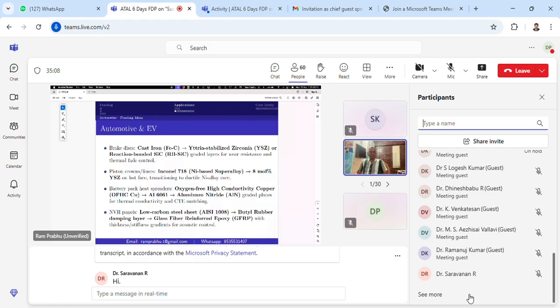So currently cast iron is used because you have a graphite lubricant inside and it has very good tribological properties. But when I expose this cast iron to the high energy braking conditions, because of the high temperature, thermal softening happens, it loses its thermal performance. In other words, wear resistance also will be poor, the life will get affected. Braking performance is also poor because of the high temperature assisted thermal fade, we call it brake fade problem. So the coefficient of friction will drop with the increasing temperature.